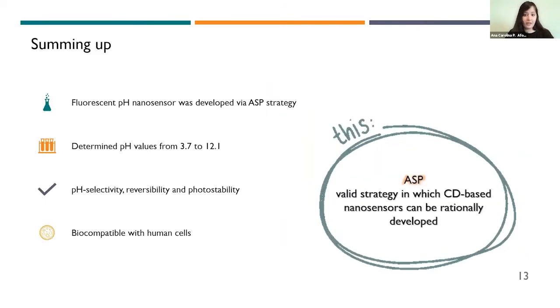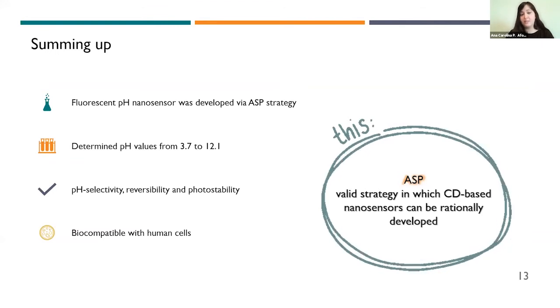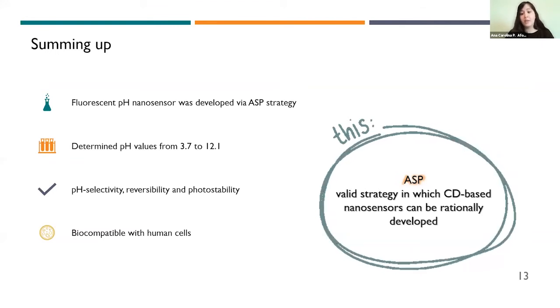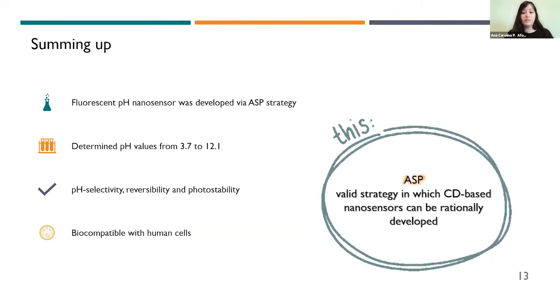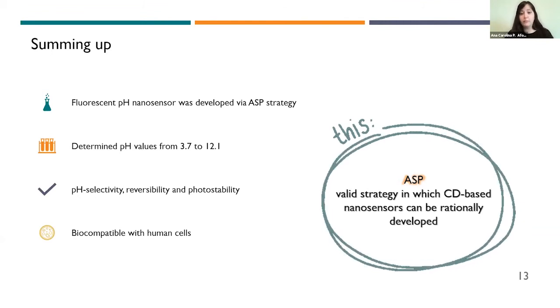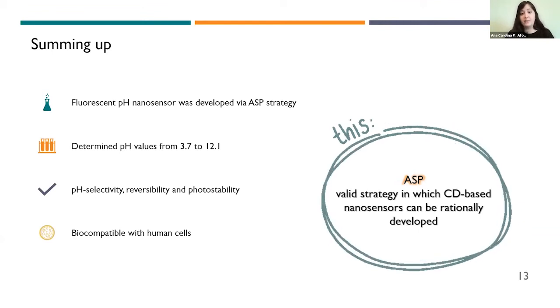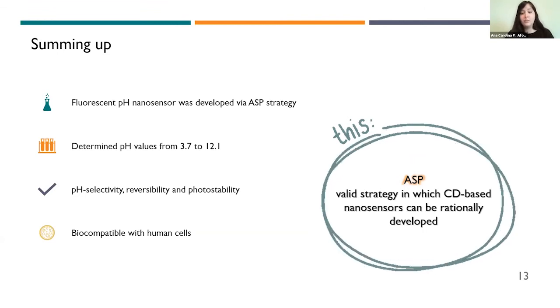To sum everything up, a fluorescence pH nanosensor was rationally developed by using an active surface passivation strategy. The carbon dot can be used to determine pH values from 3.7 to 12 by fluorescence enhancement at 525 nanometers, showing also pH selectivity, reversibility, and photostability, while being compatible with human cells. Therefore, the fluorescein-coated carbon dots show potential for intercellular pH determination.